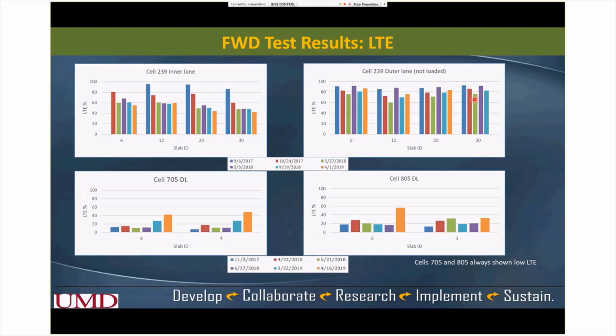We saw the load transfer efficiency in the inner lane continue to drop. That means the concrete's interlocking or fiber contribution is decreasing with time. The inner lane is the lane where MnROAD applies the load. The outer lane is not loaded, so load transfer efficiency remained almost the same. That means the aggregate interlocking or the fibers are not getting fatigued. No load, no fatigue. So here the fatigue is influencing the load transfer.